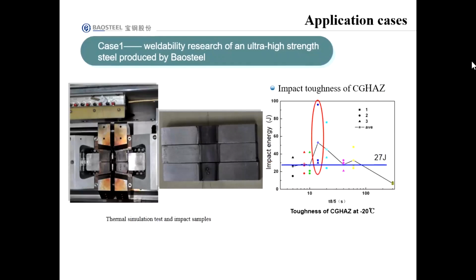This picture shows the impact toughness of a simulated coarse-grained heat affected zone with different cooling rates at a low temperature of minus 20 centigrade. From this picture, it is known that the coarse-grained HAZ has the best property when the t8/5 is 14 seconds.